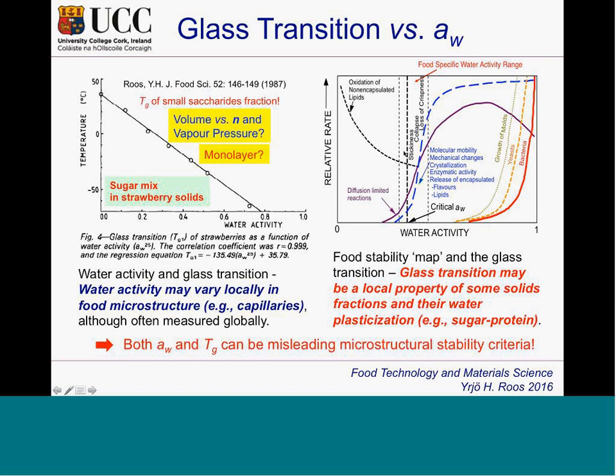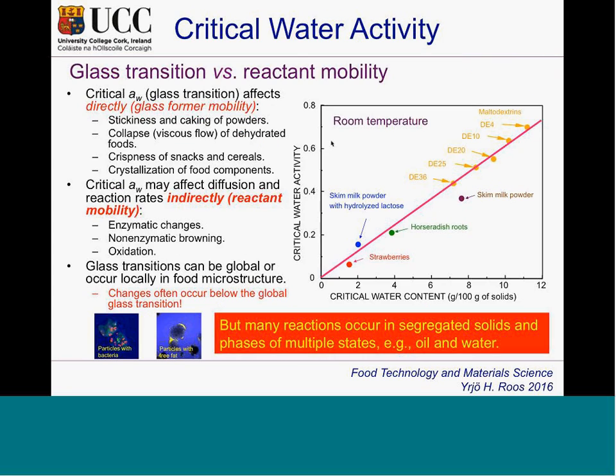Oxidation is very different because you are looking at a phase of the reaction that often happens in the glass formers. It happens in compounds that are dispersed within that. The diffusion of oxygen in the glass may happen, but often it's a barrier. If critical water activity and the reactant mobility, we say that the glass transition actually is a property that is directed to glass former mobility. Then if you look at the diffusion and reaction rates, we have an indirect effect.